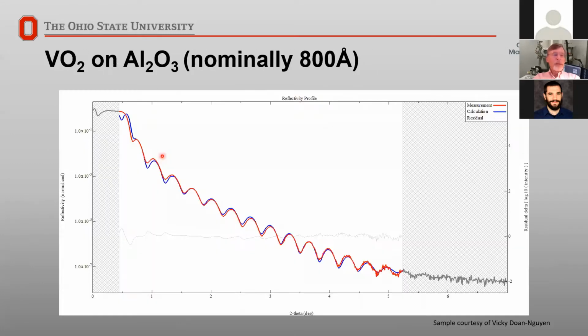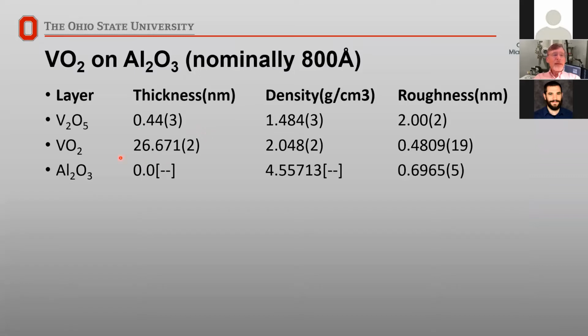Now we had another sample come in of vanadium oxide grown on alumina. And the grower told us that it was 800 angstroms, or 80 nanometers thick. Well, we came through and we started modeling this and discovered that the vanadium oxide was only 26 nanometers and not 80. So it was less than a third of the actual thickness that they thought it was. So just as a word of warning to those people who have collaborators, trust but verify. It's hard to grow things exactly, and sometimes the calibrations in the growth chambers are not that great. So we fed this back to the collaborator, and I think he is adjusting his system a bit more.